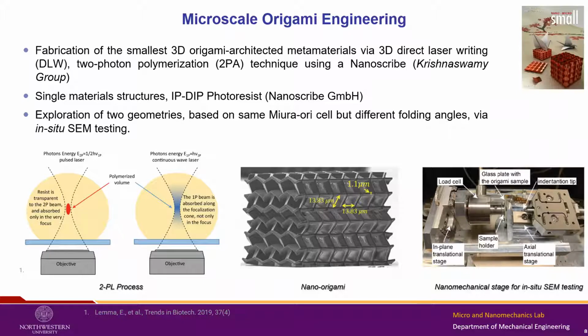We did this with a single material, which is an IP-DIP photoresist, and we explored two different kinds of geometries based on some geometric assembly of these Miura-Ori cells. Once we fabricated these structures, we transferred them to a glass slide, and we mounted them on a nanomechanical stage, which is shown to the right here. And we did some compression tests on these structures.